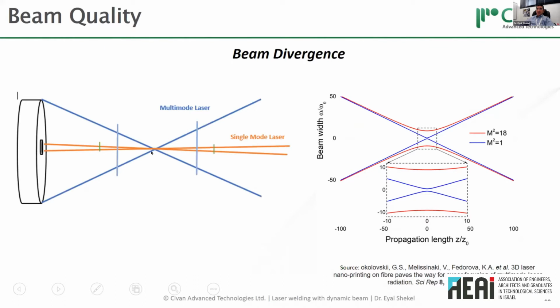The other thing is that the depth of focus is much bigger in a single mode. So what you see here is a single mode beam that starts from a smaller aperture, gets to a very small spot, and this small spot is maintained over a large depth of focus. Whereas in a multi-mode beam, in order to get to a small spot, you have to use big optics and focus the beam very sharply, but then your depth of focus is very small, meaning that when you move a little bit out of focus, the beam size becomes very big.